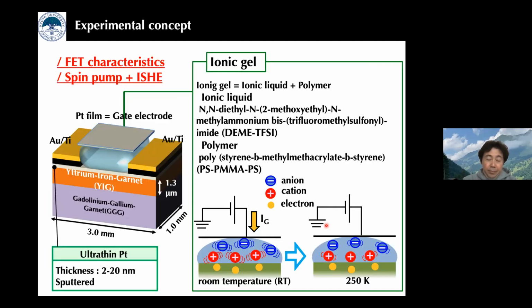Okay, so this is the experimental concept. As in the case of single-layer graphene, we use yttrium iron garnet, and an ultrathin platinum film is evaporated on top of it. An ionic gel gate insulator is placed on top of the ultrathin platinum, and we apply the gate electric fields via the platinum film.